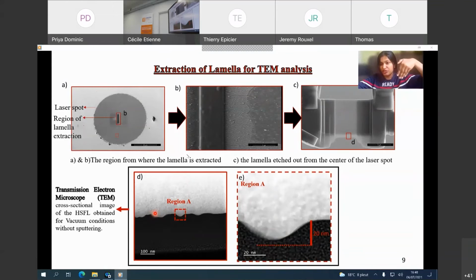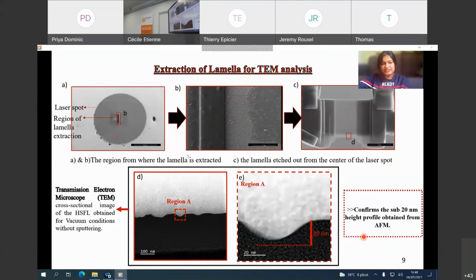So here you can see the inverted image of the HSFL. Here is the tungsten, and these are the relief and valleys corresponding to the HSFL. And then figure E is a very enhanced image of the relief of the HSFL, and the scales on the figure indicate that indeed the amplitude of the HSFLs obtained is sub 20 nanometer, which agrees with the AFM analysis. So ultimately the morphology of the HSFLs has sub 100 nanometer periodicity and sub 20 nanometer height profile.